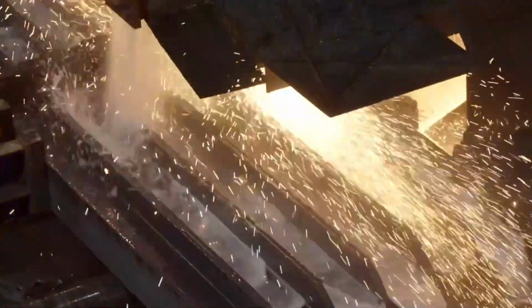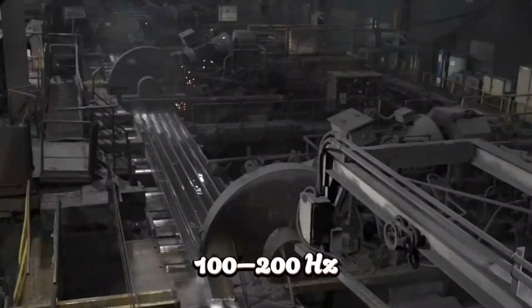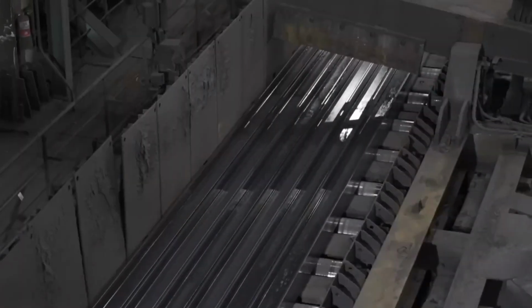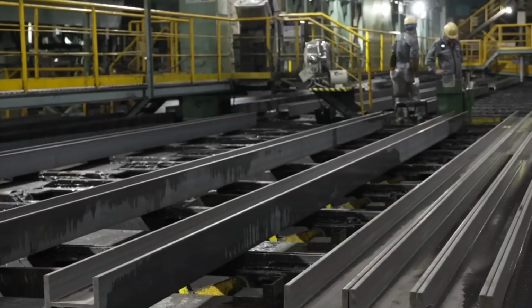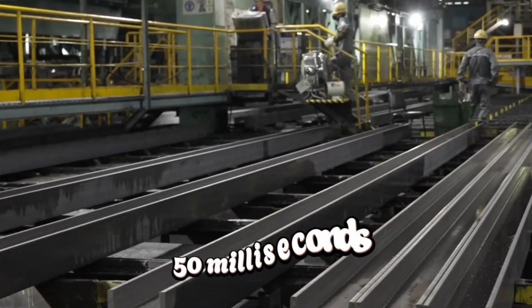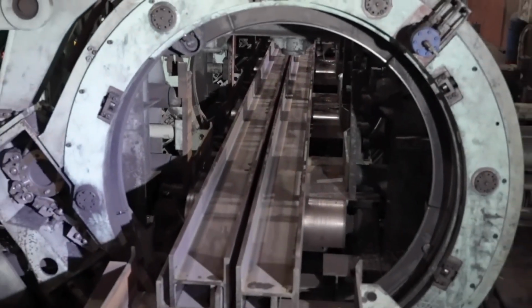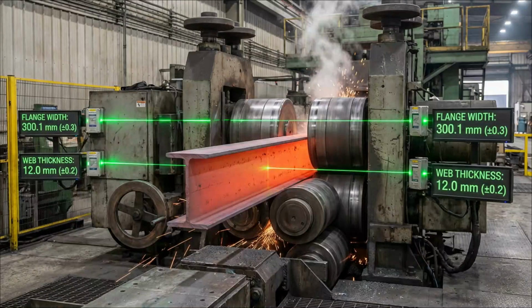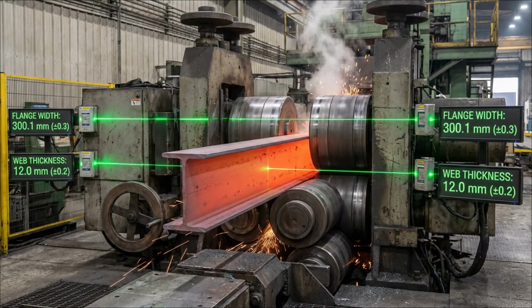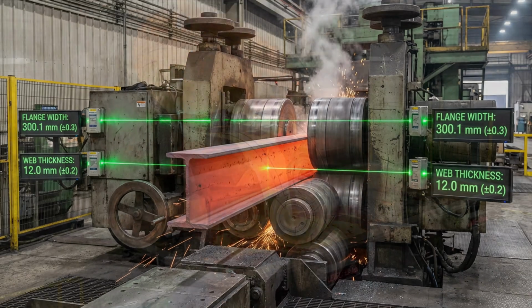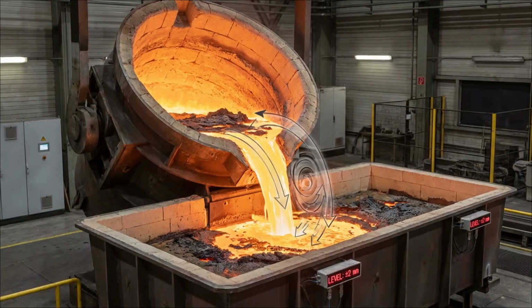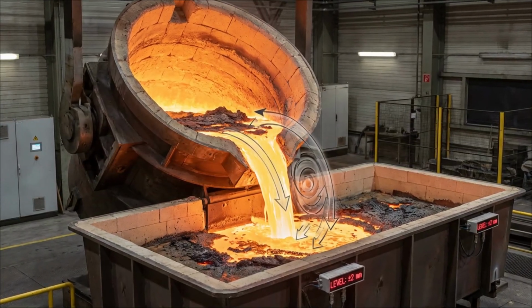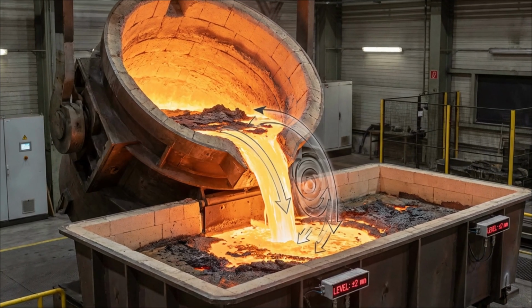Continuous casting survives because of its sensor grid. Thermocouples monitor mold temperature at 100 to 200 Hertz. Powder feed systems correct lubrication flow 10 times per second. Withdrawal load sensors adjust roller pressure every 50 milliseconds. Spray zones pulse water in tight temperature windows, synchronized to billet speed. Even the oscillation waveform is corrected live to maintain powder melt rate. This closed-loop system, temperature, pressure, lubrication, and speed, keeps the shell intact while the core remains liquid.